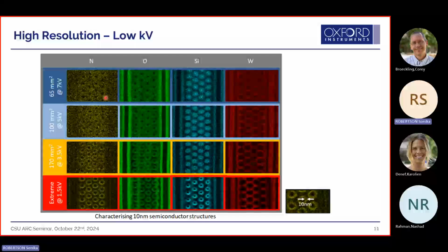The time difference? Yeah. So time difference is actually not that much. The difference is sensor size. So all of these were somewhere around 30 to 45 minutes acquisition time, but the difference is sensor size. I don't know why they came up with this campaign, but the name of it was Size Does Matter. And so 170 millimeters square, being the largest, will collect significantly more counts.